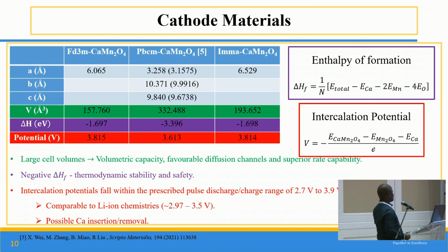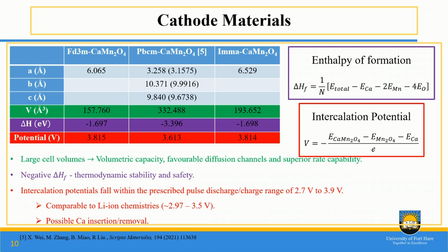And then we calculated the projected intercalation potentials. We find that they fall within the prescribed pulse discharge range of 2.7 volts to 3.9 volts. And we have also noted that they are very much comparable to the ones of lithium-ion chemistries, which normally range from 2.97 to 3.5 volts. Then what does this tell us? It tells us that these structures are able to reversibly insert and also remove calcium without any distortion of the material.